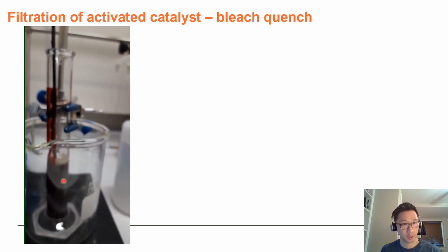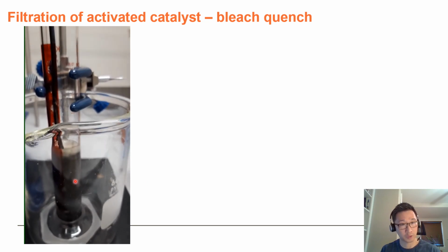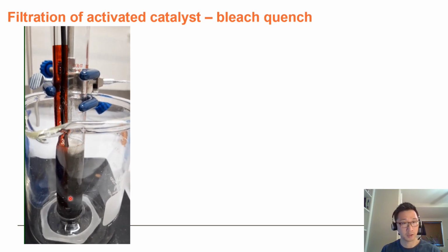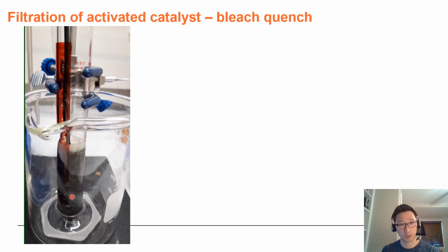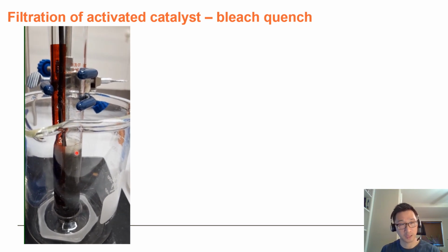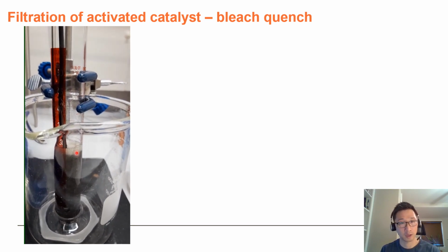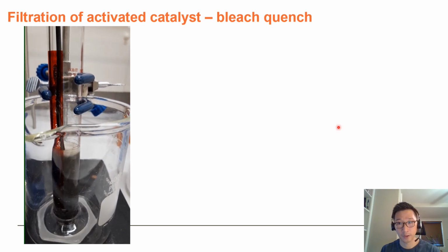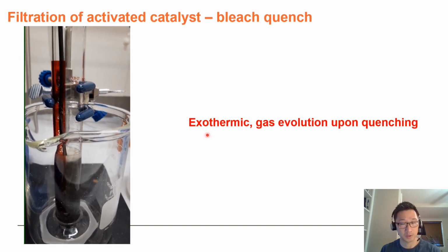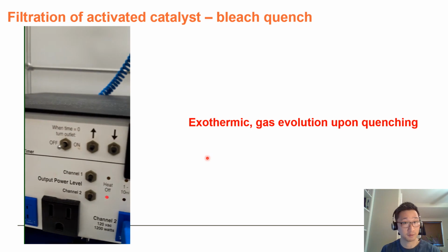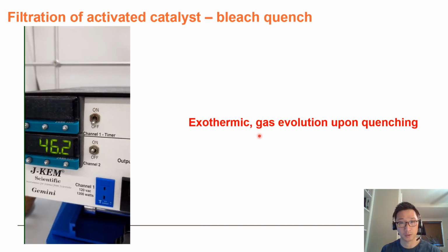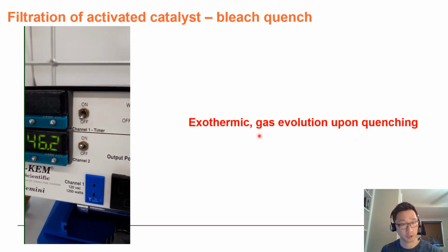Now, keep in mind, this is not really a controlled reactor. This is open to air, so there's probably some heat loss to the environment, and so that 20-degree exotherm is probably not indicative of the actual heat that's generated. There's probably more heat than that. And thus, just qualitatively, we can see that the bleach quench is not safe. It's exothermic, and we see a lot of gas evolution upon quenching.